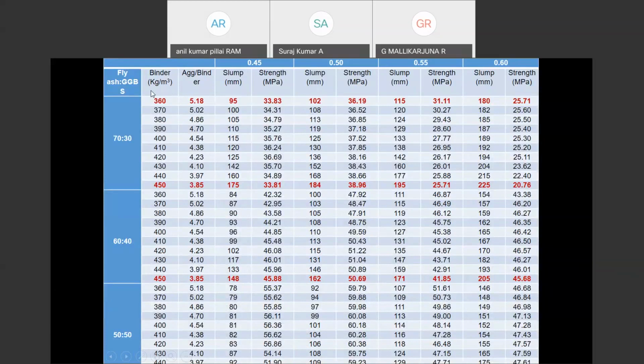Here the binder content is from 360 to 450 kg per meter cube, with the aggregate to binder ratio based on whatever slump values we are going to get. If you want to select a certain slump value from 95 to 175, your required strength is also taken here. Like this, we have developed the entire charts for the mix design methodology, so that whatever the required strength, from 20 MPa to 60 MPa, you can get here. If you want to go for 60 MPa strength, you have limitations, with less binder content or more binder content, we can get the required strength here.